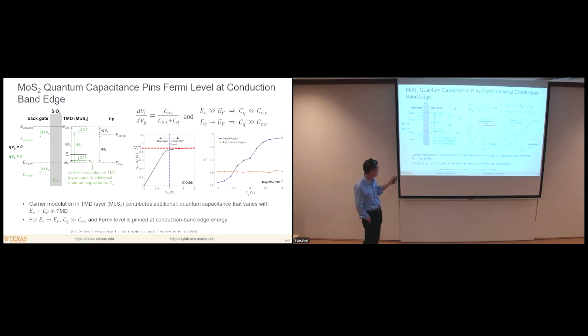And so if we look at this in more detail, the main point here is that when we apply a backgate voltage, say a positive backgate voltage in this case, then these energy levels move down. And as the conduction band edge energy approaches the Fermi level, then there is accumulation of electrons in this layer. So there's a capacitance associated with that electron accumulation. This is referred to as the quantum capacitance. And that combines with the capacitance of the oxide layer over here to give us the relationship between the backgate voltage that we apply and the change in the potential in the sample layer.